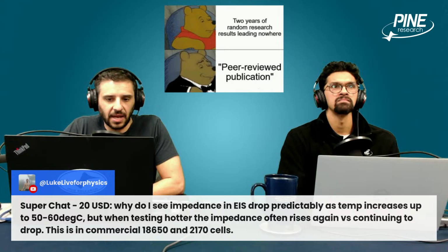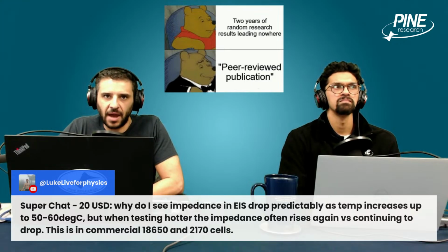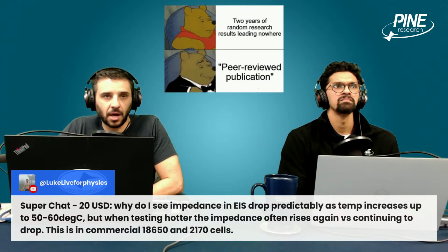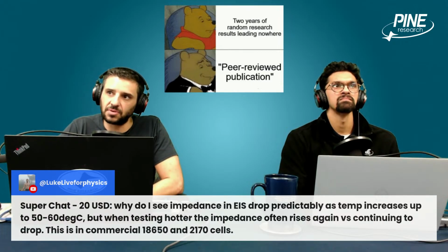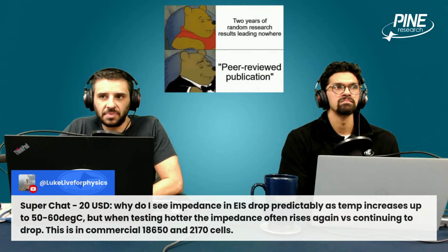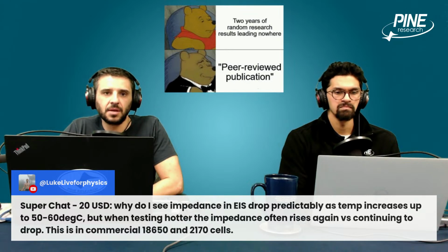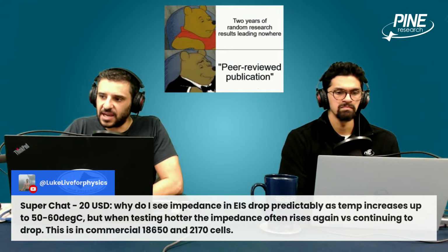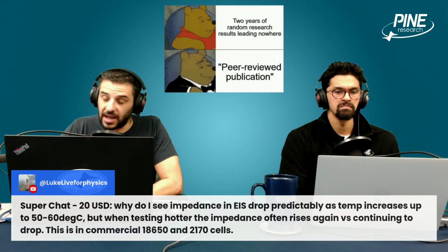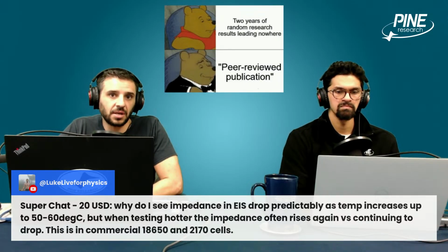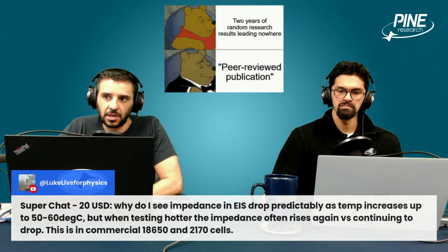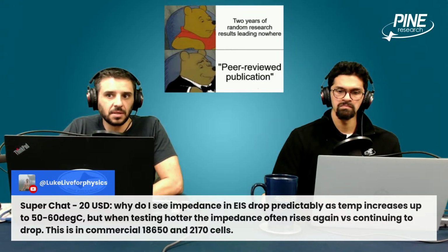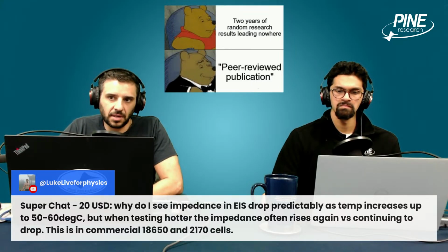That could be a very bad sign. Batteries can withstand higher temperatures, but you start to get other things happening. So you could have degradation of the anode, degradation of the cathode, degradation of the electrolyte. One of the reasons why your impedance might be going up is because the SEI could be collapsing. If the SEI collapses, you could have all kinds of bad stuff start to happen. You could have degradation. You could have severe performance losses. All of these things could very well increase the impedance of your system.